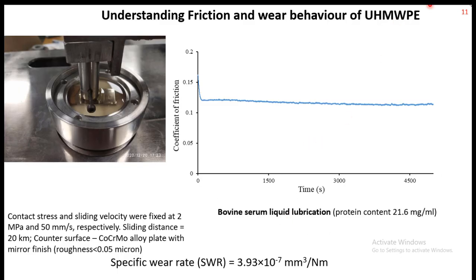So let us try to understand these materials that we are working with. Basically, these are within our control, the materials that we use, UHMWPE and some other materials. If you work with UHMWPE, you will understand how the coefficient of friction will show. In general, in a dry interaction, that means if UHMWPE is dry sliding against a metal surface, you will get quite a high coefficient of friction. But if there is lubrication with bovine serum liquid, then the coefficient of friction will come down, and this shows that it responds to the lubrication.